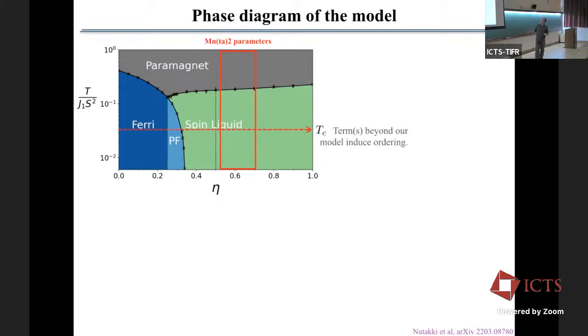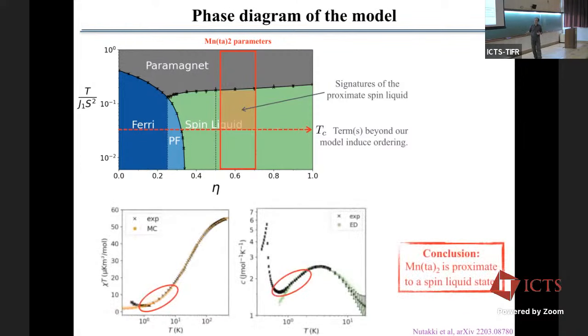Then we know that in experiments, there is a transition temperature, and if we rescale it by the right parameters, this transition temperature happens here, which means that there is this whole region here at finite temperature where we can expect signature of the proximate spin liquid. So we know in the minimal J1, J2 model, this region is a spin liquid. In experiments, we find a transition temperature at low temperature, but we know that at finite temperature, we should see signature of the spin liquid, which means that if we do experiments in this region, here or here, between around 1 to 2 Kelvin, we should find signature of a spin liquid. And so manganese triazolate is proximate to a spin liquid state.